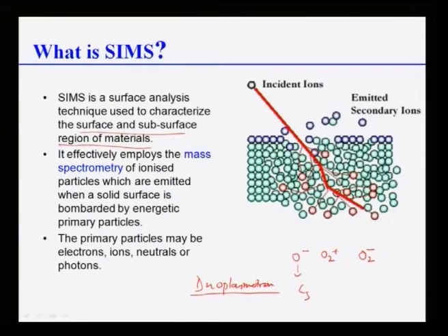Basically this is nothing but a sputtering process. You are bringing in primary ions and sputtering. You can sputter more material effectively because of their greater mass, and it is normally used to extensively measure the different isotopes. And when you use insulating material, you can always use Cs plus beams. As you know, most of these are surface ionization processes, so they lead to heating up of the samples, and sometimes it can create other problems also.